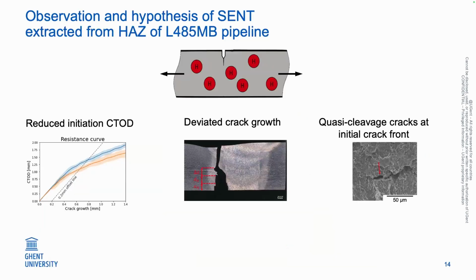So to take a small recap of what I just presented, we tested the heat-affected zone by single edge notch tensile testing, and we saw reduced toughness of the hydrogen recharged specimens, which can be linked to the quasi-cleavage in the initial crack front, with also the small cracks that we observe there. Looking at the cross sections, we see deviation of the crack paths, where we have multiple hypotheses.